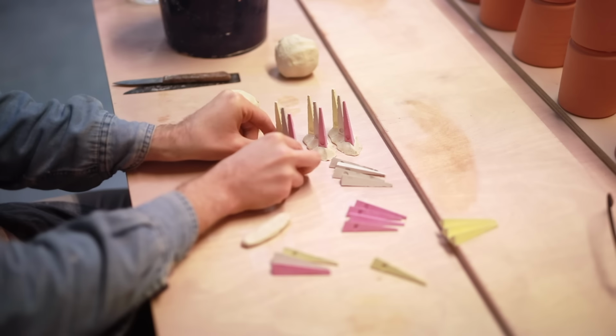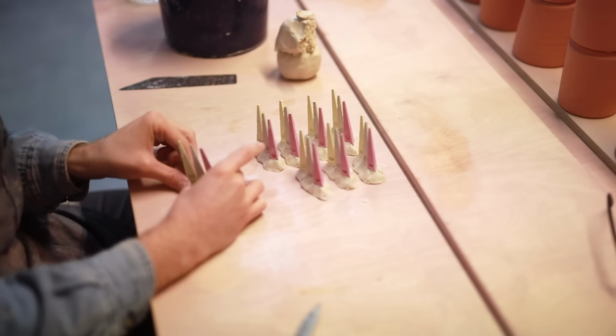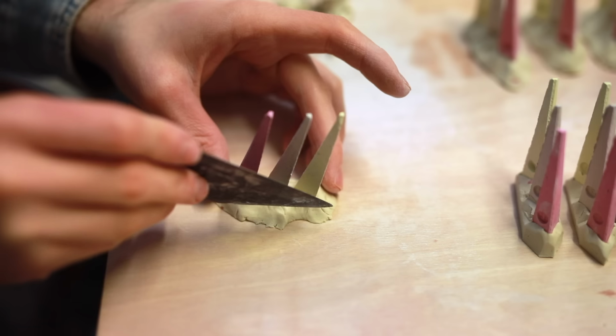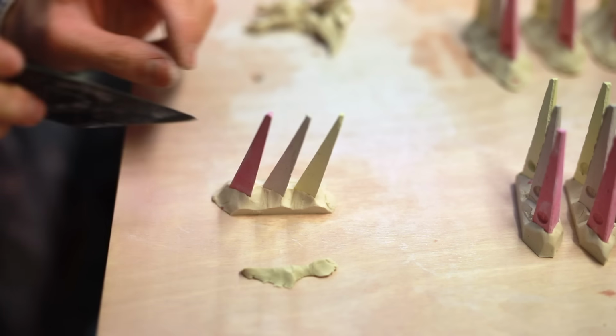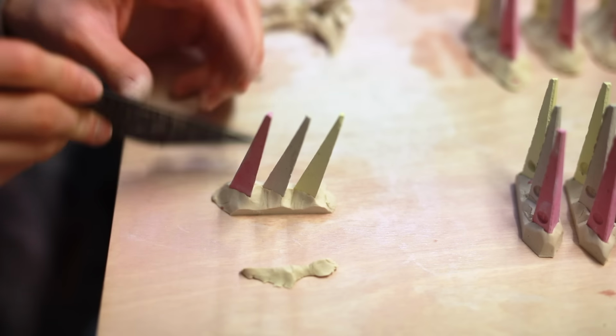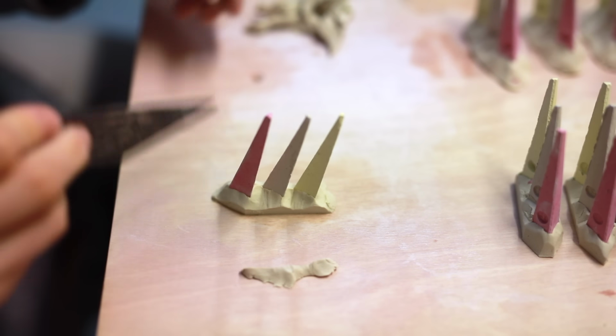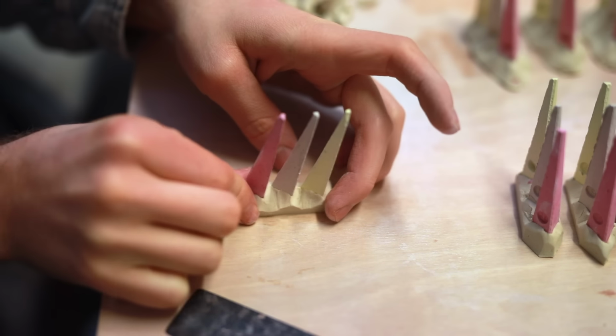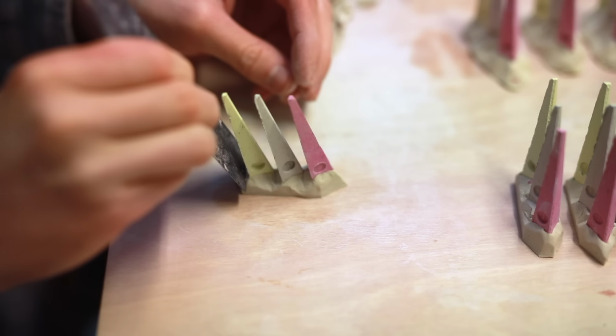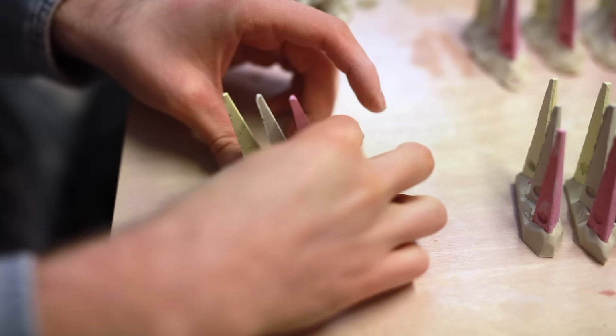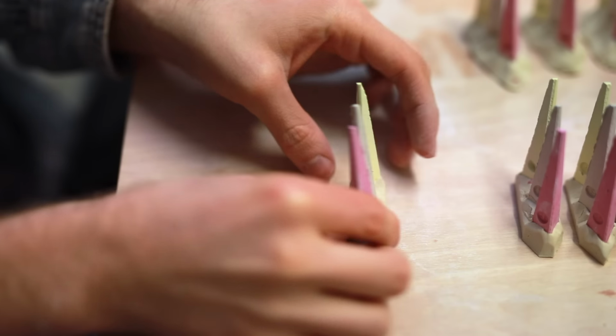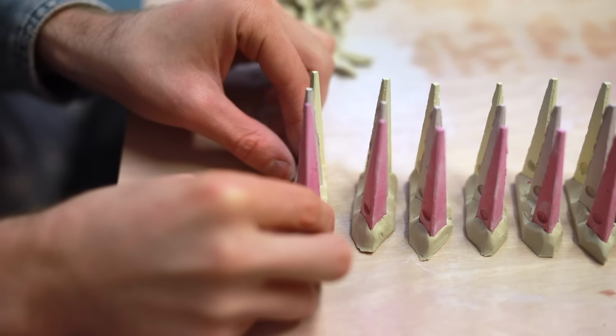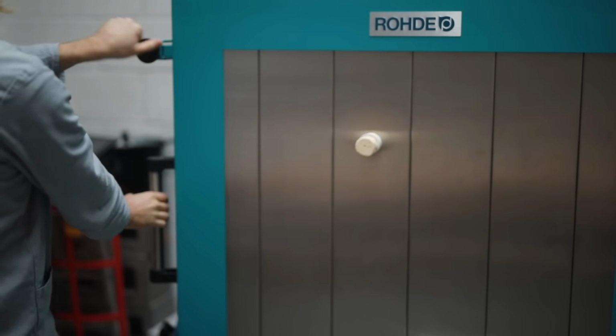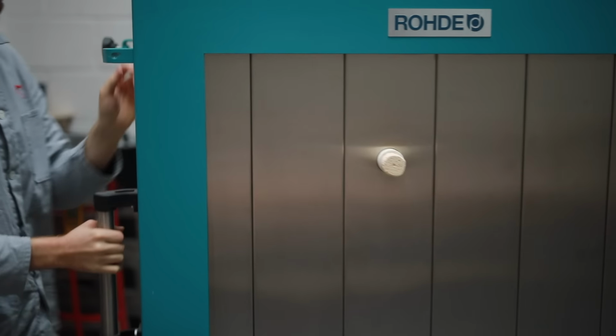As the internal temperature of the kiln reaches certain points, these cones bend over respectively, very, very accurately. And more importantly than just measuring simple temperature, they measure heat work too, which is heat over time. It's these cones really that I use to judge each firing, which makes them incredibly important. You couldn't really fire a gas kiln without them. You'd be firing blind doing so, which is never advisable. I only need 2 of these cone packs per firing, but it's easier just to make a whole lot at once, I find.